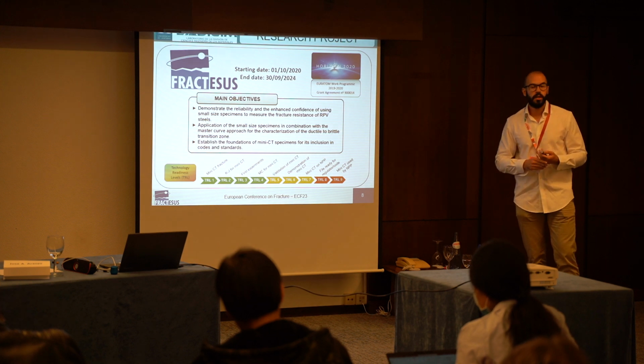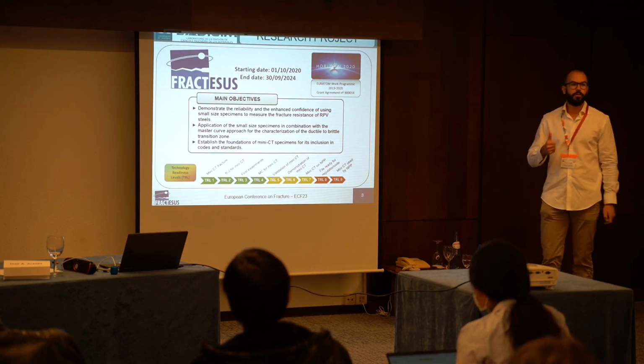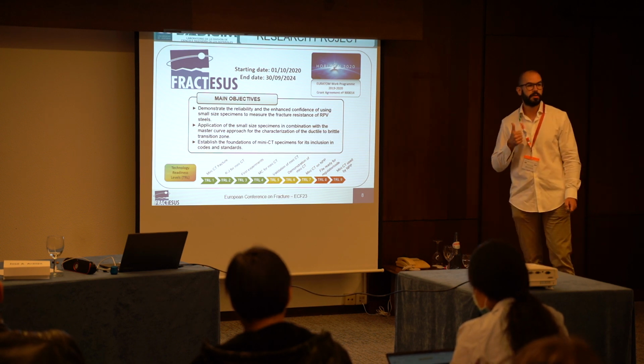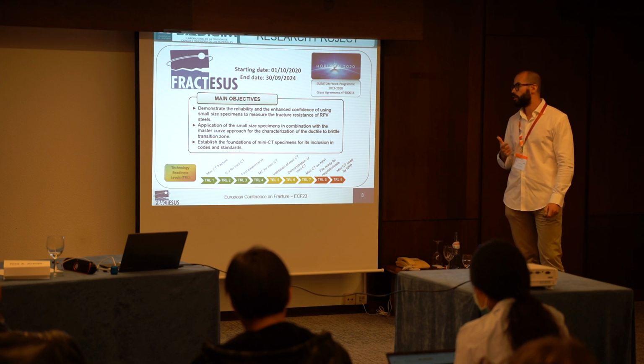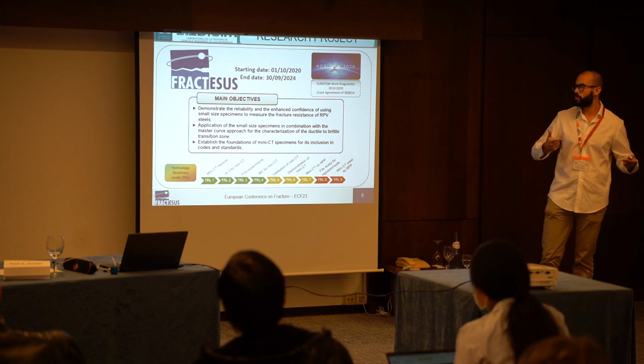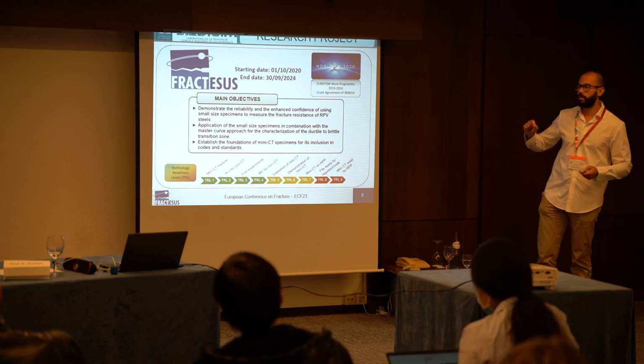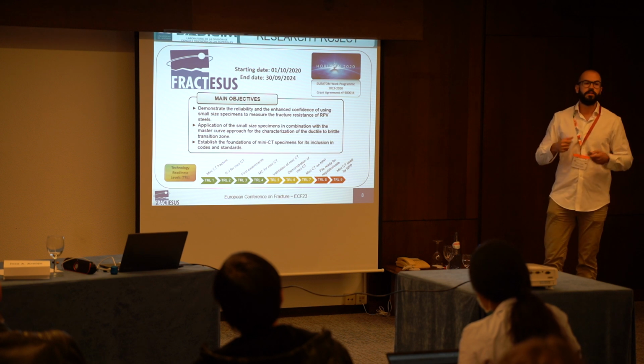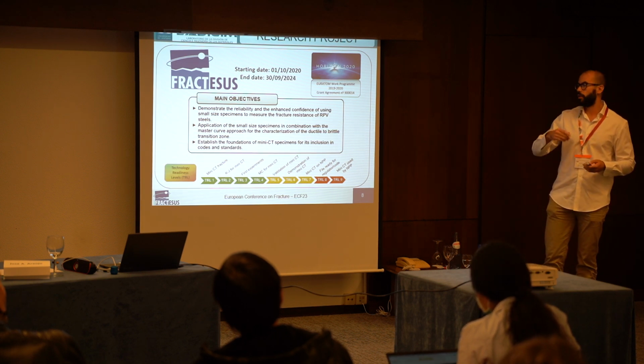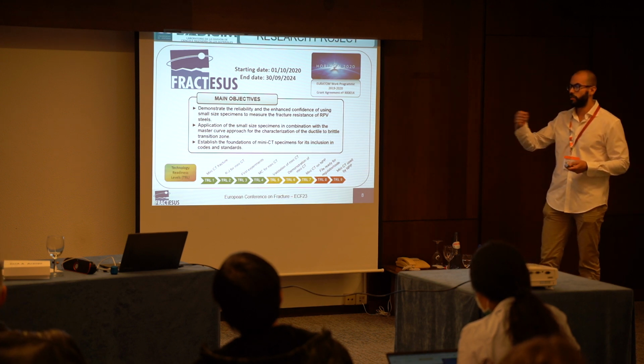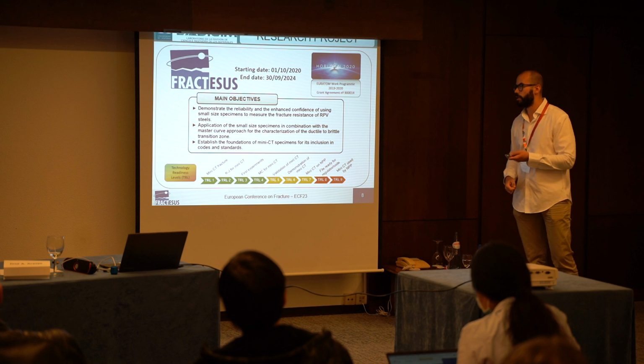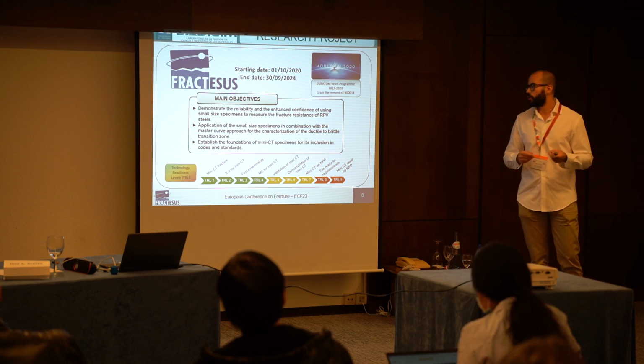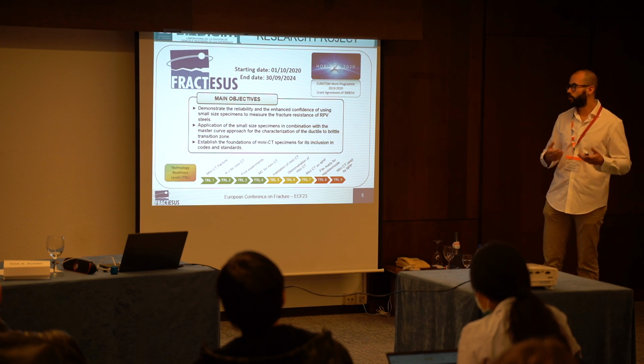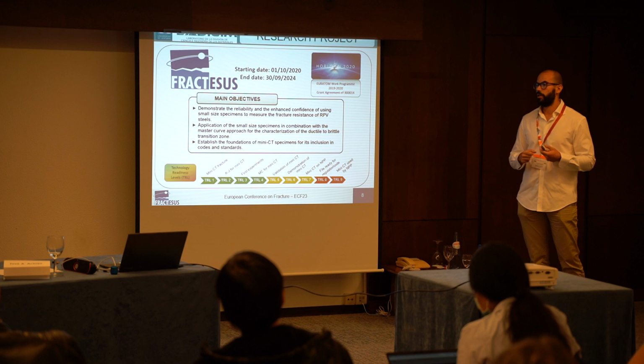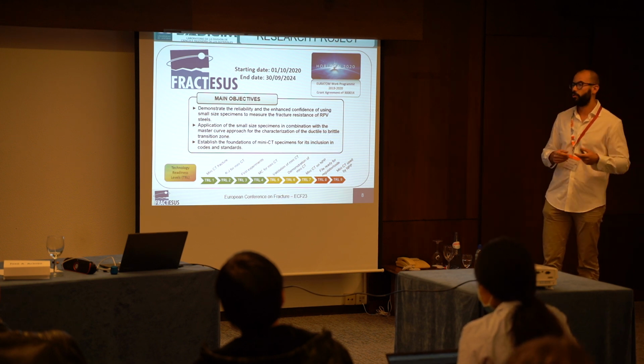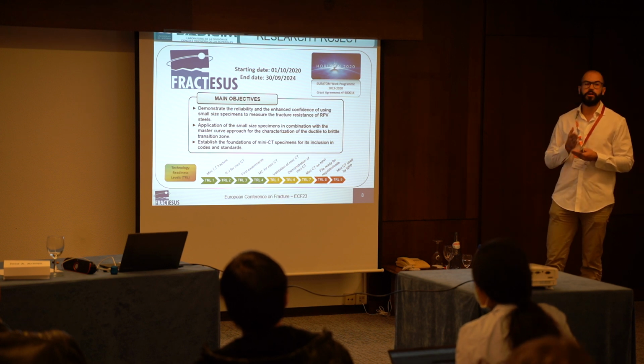The main objectives of this project are to demonstrate the real ability to use the mini-CT specimen to measure the fracture toughness in RPV materials, to demonstrate applicability to use these specimens in combination with the master curve approach to characterize the material within the ductile to brittle transition zone, and establish the foundations for the use of mini-CT specimens in future codes and standards. With all this, following the technology readiness levels proposed by the European Commission, we can assume that right now we are at level 5, and thanks to the FRACTESUS effort, we are going to move to level 7. Meaning that the mini-CT specimen will be validated and demonstrated in a real operational environment.